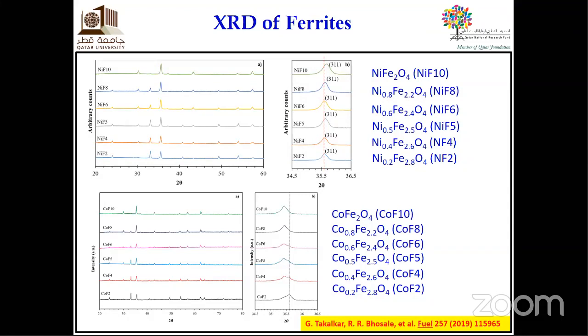In addition to XRD, we did the EDS analysis also, which helps us to further confirm the elements involved and what are the percentages. So these are the nickel ferrite, cobalt ferrite we have synthesized. After that, we also did the BET surface area analysis, and because it was calcined at 1000 degrees Celsius, the surface area was around 10 to 15 square meters per gram. After that, we did the SEM and TEM analysis.